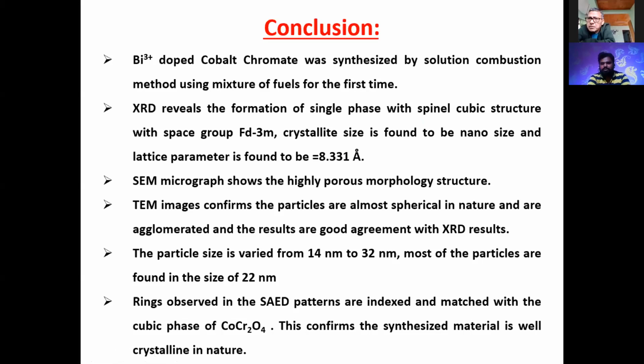The particle size varies from 14 nanometer to 32 nanometer. Most of the particles occur at 22 nanometer. Rings observed in the SAED patterns are indexed, and these indexed HKL values match well with the spinel cubic phase of cobalt chromate. This confirms the synthesized material is well crystalline in nature. The energy gap is found to be 2.7 electron volt. The activation energy is found to be 0.74 electron volt.